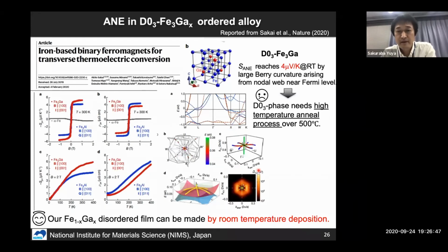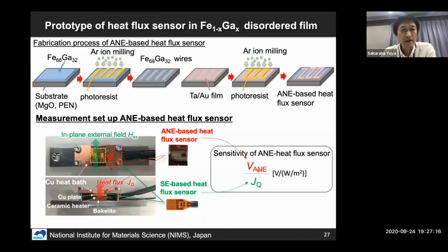This is a very impressive paper, but what we want to emphasize is that the formation of the DO3 phase needs high temperature annealing over 500 degrees C. But our disordered iron gallium film can be made by just room temperature deposition, which is more suitable for practical application. To prove it, we fabricated an anomalous Nernst effect-based heat flux sensor using the disordered iron gallium film. Because we don't need any thermal treatment, we can deposit this film not only on a solid MgO substrate, but also on very flexible substrates, for example polyethylene naphthalate film or polyimide film, which have very low thermal endurance.